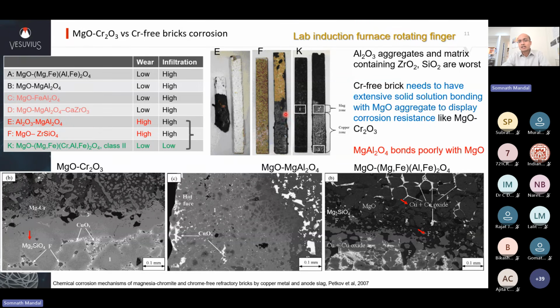And you see that this is after, I think, 24 hours, you see very little corrosion. And then this is alumina spinel before and after corrosion. And after corrosion, you see even after 2 hours, it was completely gone. It was completely washed away. This is magnesia zircon. And again, this only lasted 6 hours. This was getting highly corroded. So you can see none of these are even close to the performance of magnesia-chrome. So the takeaway from this is that alumina, zirconia, silica seem to be really bad for copper application, for this kind of acidic slags.